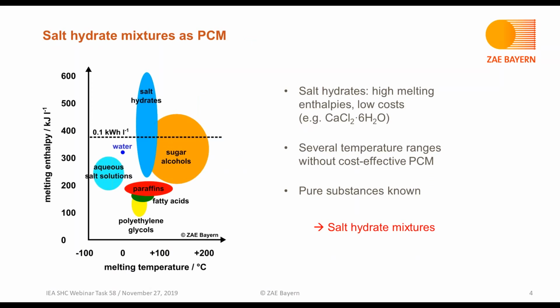For the low temperature range, salt hydrates are most interesting. On the left, you see a figure with the different material classes that are being discussed or applied as PCM, several organic and inorganic materials, and in the range from 0 to 100 degrees, salt hydrates offer higher melting enthalpies in terms of energy density per volume at comparably low costs.